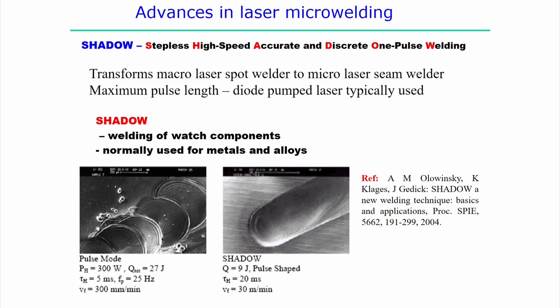In the SHADOW technique, maximum pulse length is possible in the diode pump laser, which is why diode pump lasers are typically used. Looking at two figures: in the first, the fusion zone from a pulsed laser shows overlapping spots — pulse mode at 300 W power, 27 J pulse energy, 5 ms pulse on-time, 25 Hz repetition rate, and velocity of 300 mm/min. This results in overlapping of several spots.